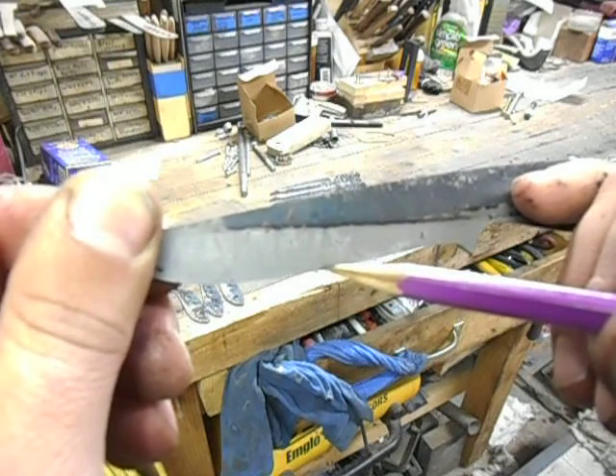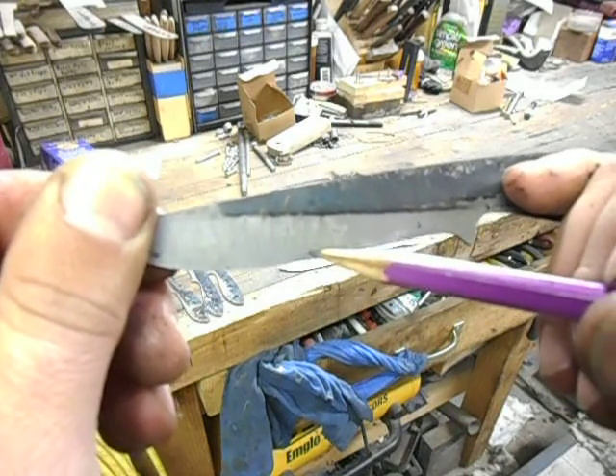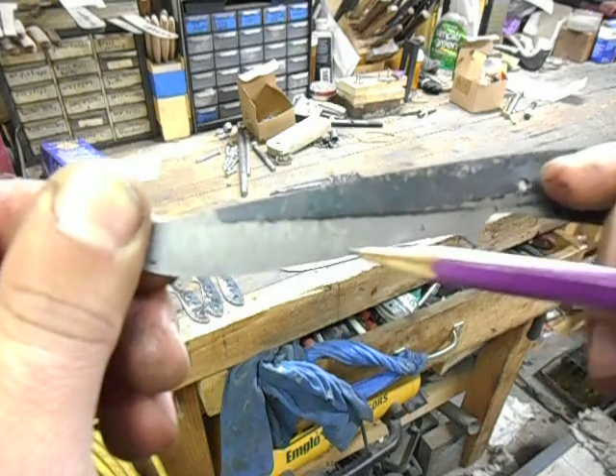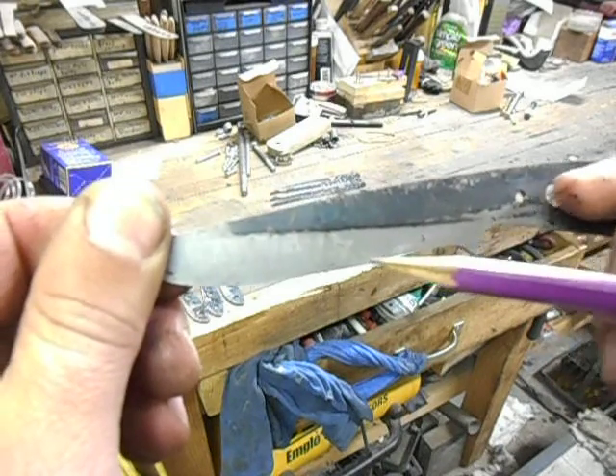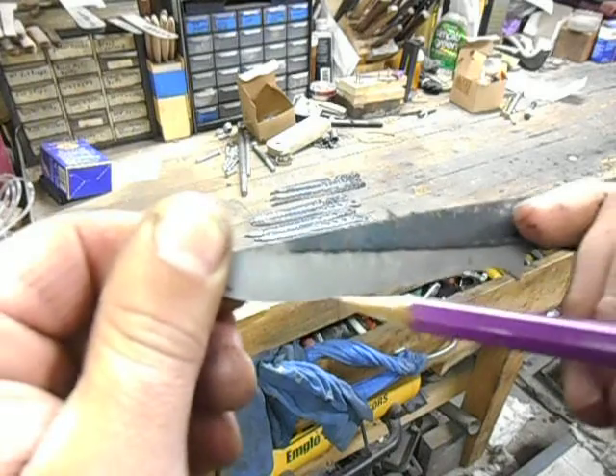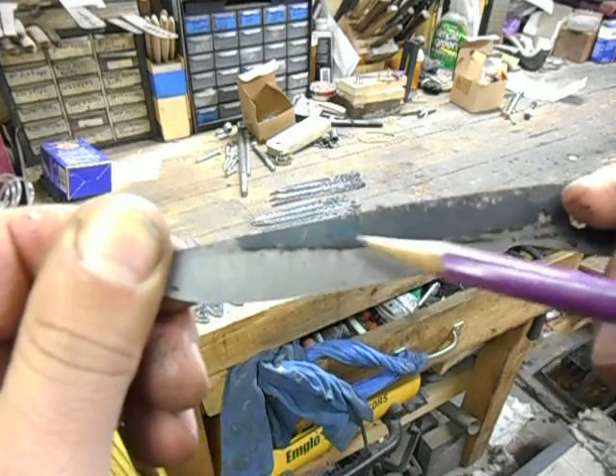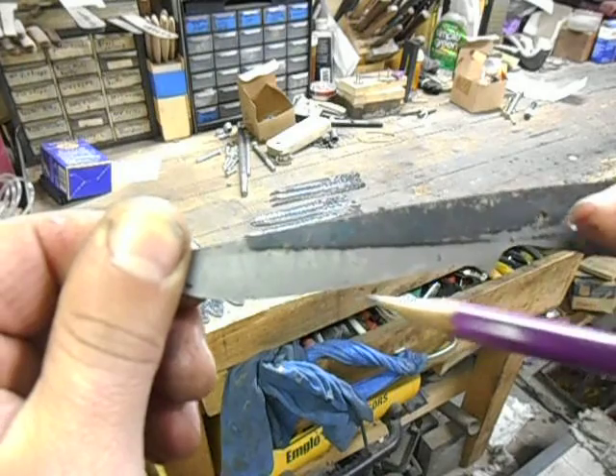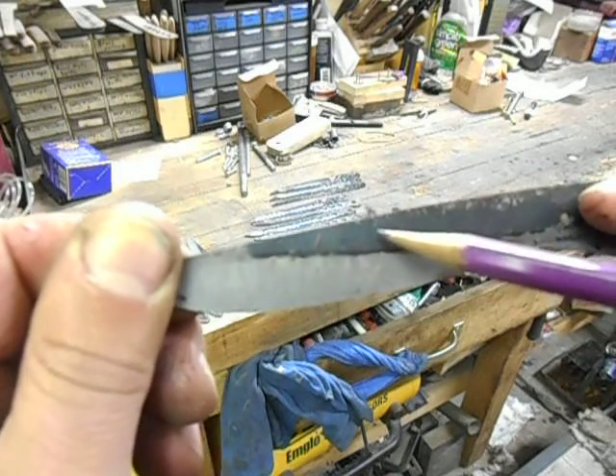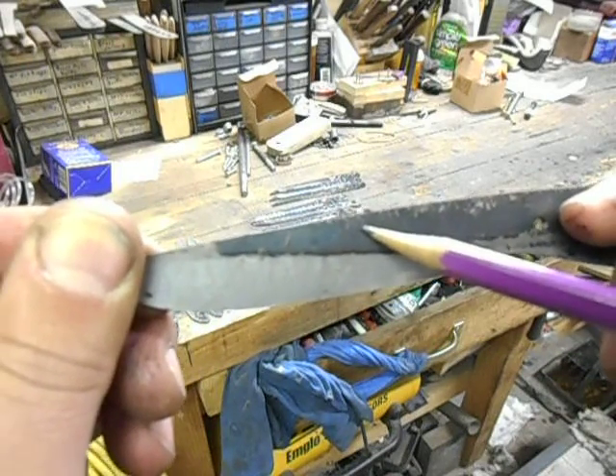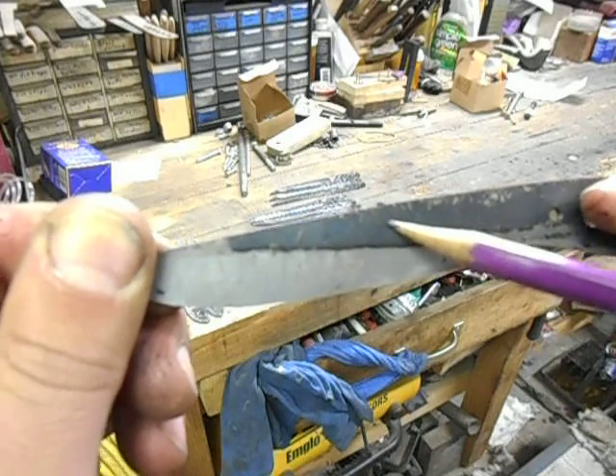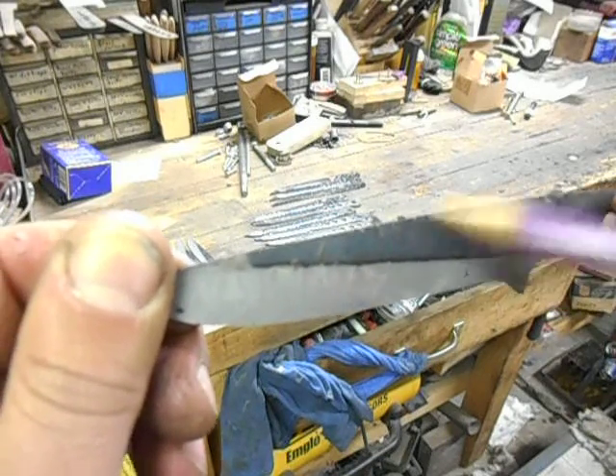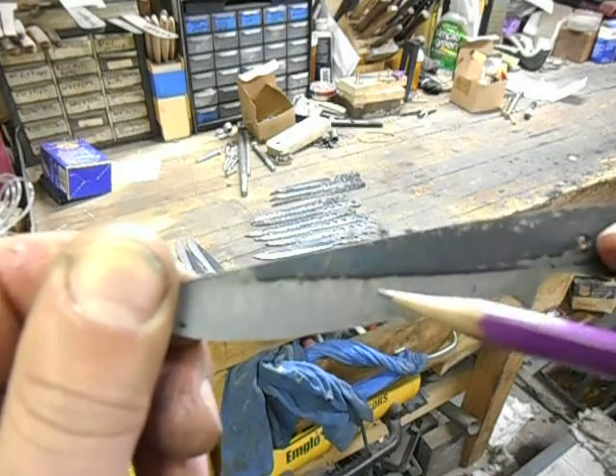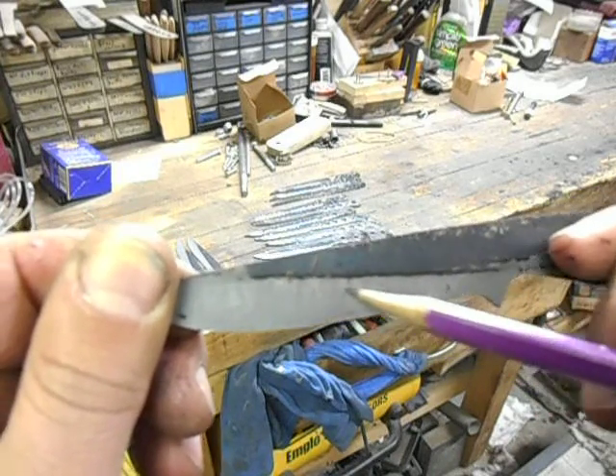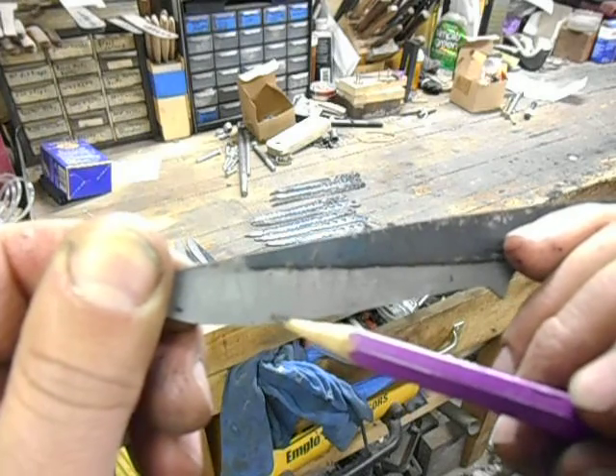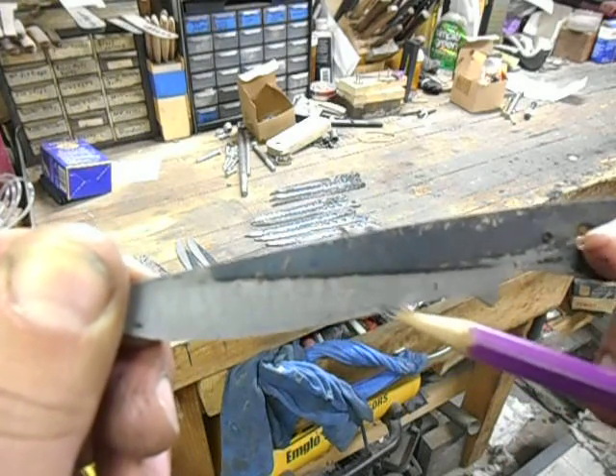That scale hanging on there is telling you that that portion of the blade was not hot enough when it went into the oil to properly harden. So if you're doing, let's say that happened on this one, you'll have the scales hanging on here, which means it didn't get hot enough to harden and it's not fully hard. There'll be some air hardening, like I say, but not fully hard. This portion will be nice and hard, but that portion at the edge, it cooled off too much to harden.